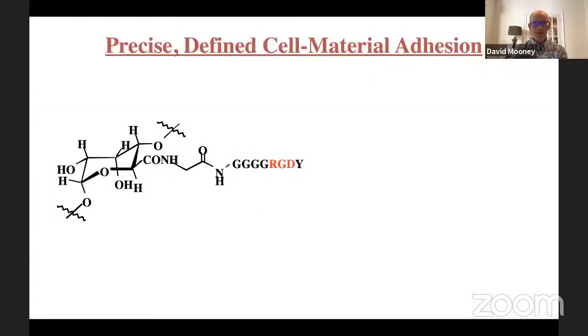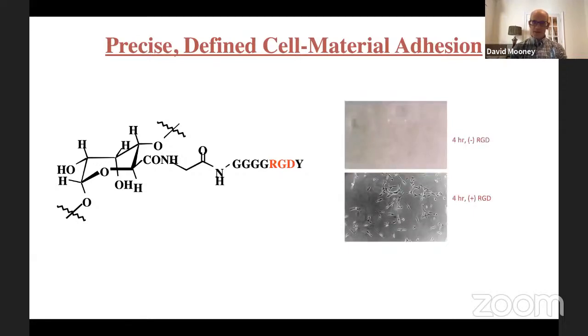Now, cells don't have a normal means of engaging with this particular polymer, which is typically derived from seaweed. So to mediate a specific and defined mechanism for cells to engage via their integrin receptors, one can simply covalently conjugate small peptides taken from sequences found in molecules like fibronectin. And the RGD sequence is obviously a very ubiquitous sequence that is very frequently used to mediate adhesion of cells to synthetic materials. And this takes a hydrogel that is otherwise non-adhesive to cells, as you can see in the top image, to one that instead mammalian cells can readily attach, spread, and function on these materials.